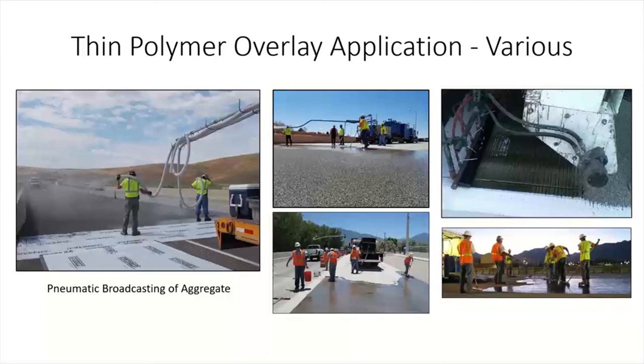Those are two considerations. If you look at the photo in the center on the bottom, they were pumping the material, but you can see the guys walking on it. And then what they were doing is they were going to come behind it with an aggregate broadcaster, and they were going to drive, and they were going to broadcast the aggregate in front of the spreader and drive across the deck. Now they had flat tires with no tread, and they were not turning the wheels on that broadcaster. So that's acceptable, but it's nice not to have to drive or walk on it.